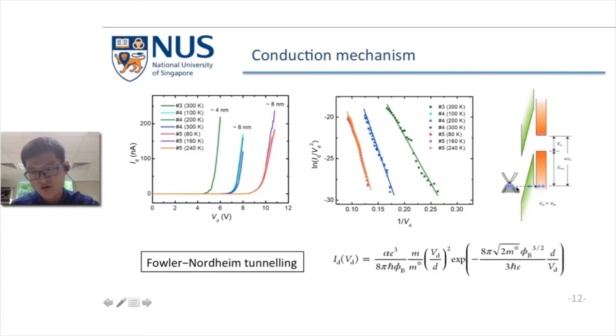The mechanism is hot holes. The holes tunnel through the triangular barrier from boron nitride and become hot holes. These holes find the electrons to form excitons, and the excitons emit light.